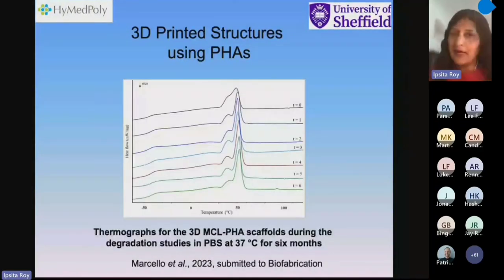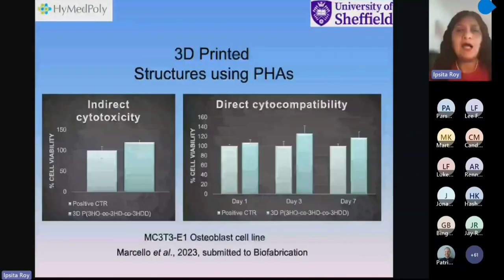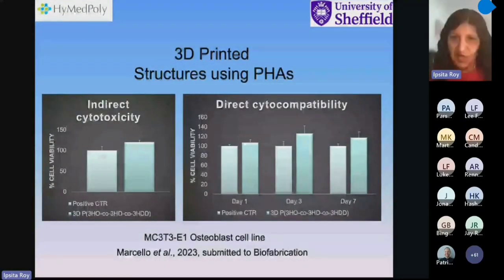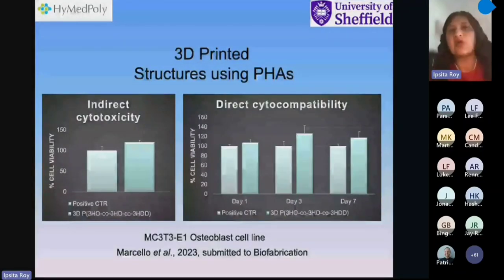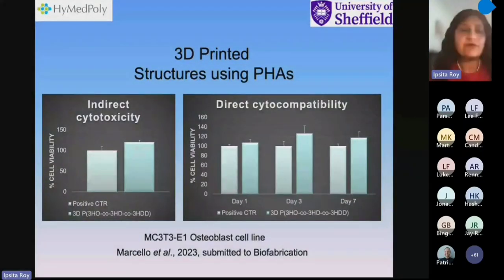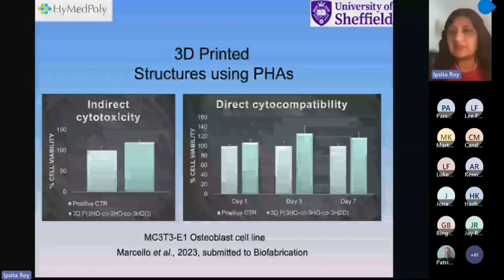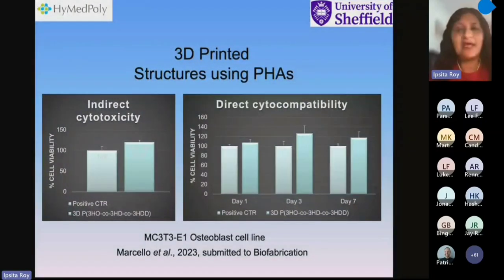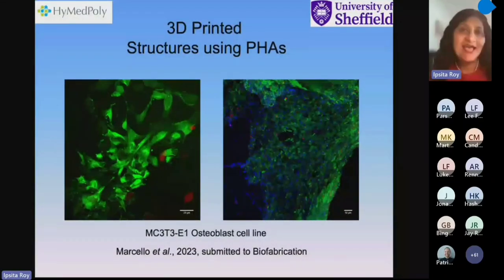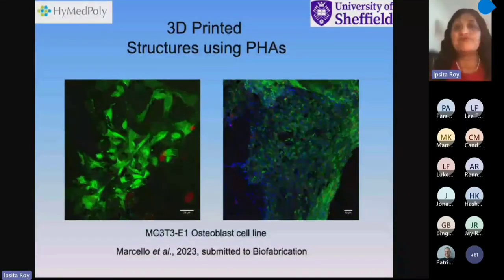And these are the thermographs of the DSC, and you can see there are slight variations in the Tg and the Tm as expected with degradation. And last but not the least, we always have to check for cytocompatibility. On the left, you see what is called indirect cytotoxicity, and the right is direct. The cells are seeded onto the material, and these are bone osteoblast cells, and they look, as you can see, very green and healthy. Green meaning healthy, red meaning dead.